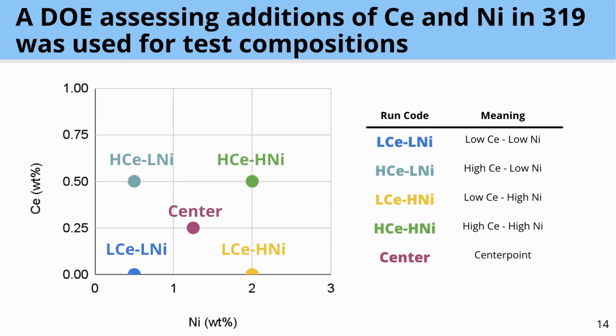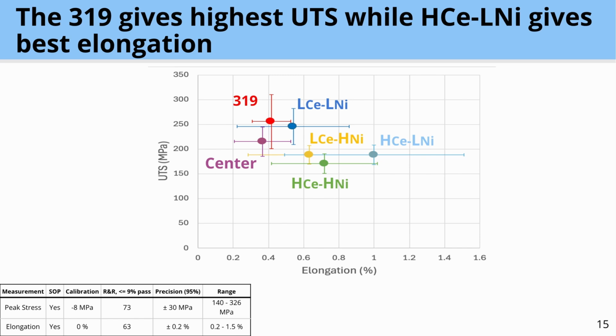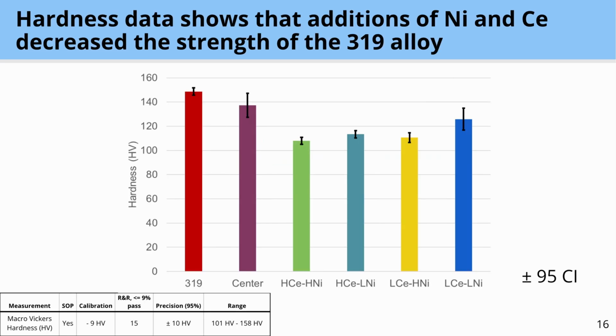We made a DOE based on this hypothesis, where we had 5 different samples with varying compositions of cerium and nickel, and we tested those via tensile testing to find the elongation and ultimate tensile strength values. Based on our test results, the 319 base alloy gave the highest UTS, while the high cerium low nickel alloy gave the best elongation. Additionally, we did hardness tests on our samples, and we found that additions of nickel and cerium correlated to decreased strength of the 319 alloy.